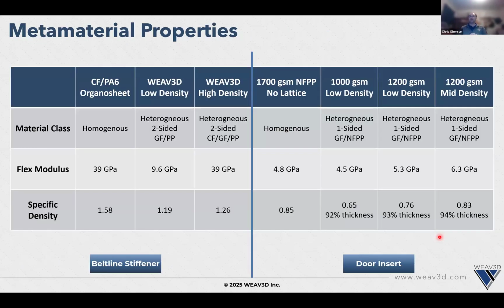So, talking about the actual metamaterial properties, if I start on the beltline stiffener, the original baseline material is a homogeneous organo sheet. It is anisotropic. It has different properties whether you're on the 0/90 or you're on the plus or minus 45s. However, those properties are the same throughout the material. You're not putting a different type of material in different locations. So it has a flex modulus of about 39 and a density of about 1.58.